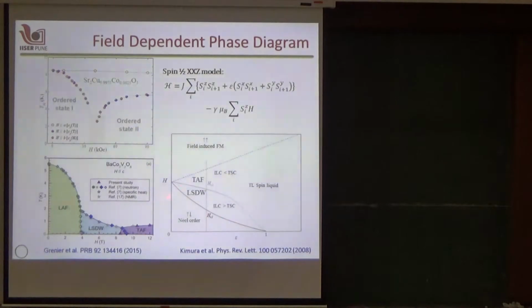And now I want to extend this comparison a little bit further. So if you are in this domain, this is the purely Ising chain, and this is the Ising like behavior, then something very curious happens. Above a certain critical field, the system goes from the Néel ordered state into a TLL state, but because of the presence of finite interchain coupling, the TLL state is not stable, and at low temperatures you then get this longitudinal spin density wave transition, which is this region. And unless the field exceeds a second critical field, you don't get to this phase, which is the transverse antiferromagnetic phase.